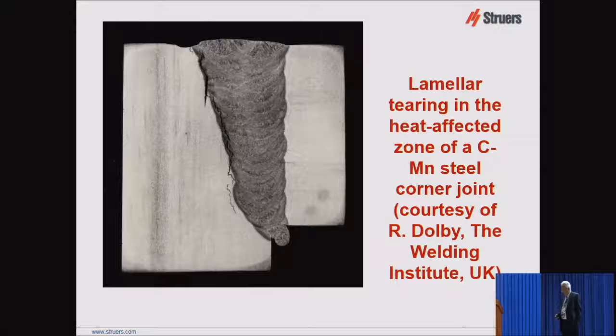And here's an example, also from Dr. Dolby at the Welding Institute, of a heat-affected zone lamellar tearing here in a carbon manganese corner joint. And you can see the fracture down here. The macro-etching is bringing up some segregation. You can even see inclusion stringers in here carefully. And then we've got the longitudinal direction this way over here, the longitudinal direction this way. And there's not a great deal of weld penetration over here, but the cracking is on the left side.